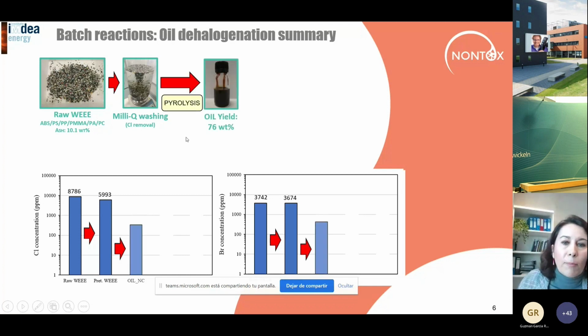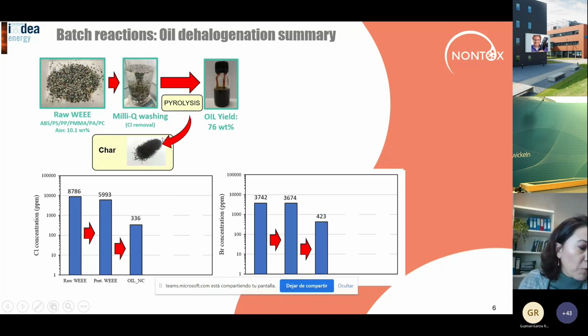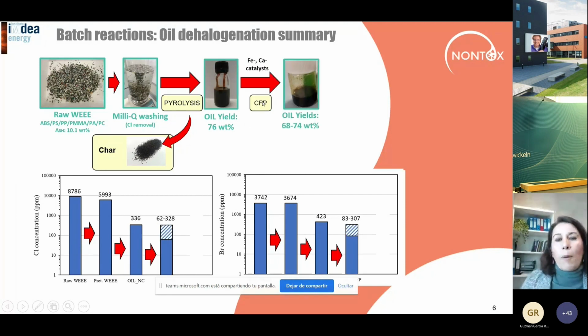Then we applied first thermal pyrolysis, the decomposition at high temperatures, around 550 degrees Celsius, but without catalyst. And we found that the oil that we obtained has a much lower concentration of halogens, as you can see here, in the case of chlorine on the left and bromine on the right. Applying a catalyst, which is called catalytic pyrolysis, just introducing a catalyst in the reaction system, we can reduce even more the concentration of these halogens in the oil. So we are improving the quality of the oil, reaching the values that you can see here.